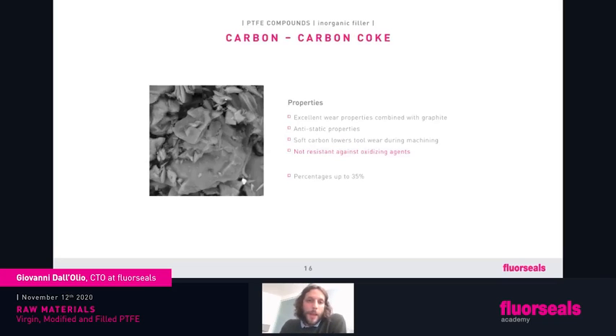Okay, here we are. Carbon. Carbon, as I mentioned at the beginning, is, together with the glass, probably the most used filler inside PTFE. We do have a lot of different carbon shapes, carbon kinds. We do have carbon and carbon coke, two big families. Carbon is a lower grade, a mine product. It's quite cheap, but has a very good performance. It is great for wear application.